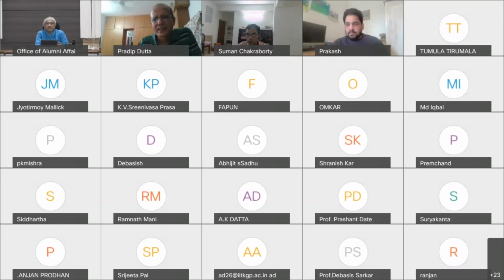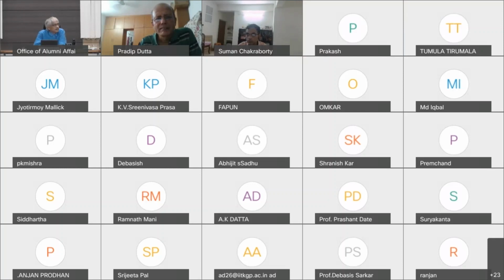Sir, good evening, sir. Sir, in one of these slides, you mentioned that while we are using this electromagnetic stirring, you observed that the core is having no dendritic structure, but the edges contain some dendritic structure. But actually at the edges, in general the cooling rate is high, right, sir? So we need to get some equiaxed grains over there. So is there any reason, sir, why you have got dendritic structure?